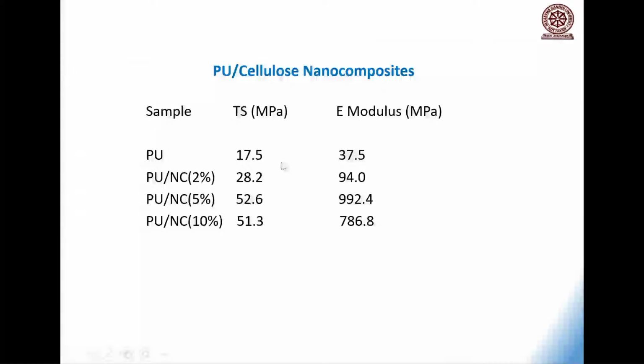So what we did is, we introduced nanocellulose from pineapple leaf fiber, 2%, 5%, up to 10%. You see, when you put 5% of nanocellulose, 37.5 becomes 992.4. A remarkable increase in modulus. And my colleague from Sao Paulo University was very happy. And we made a series of nanocomposites of PU and nanocellulose from pineapple leaf fiber.